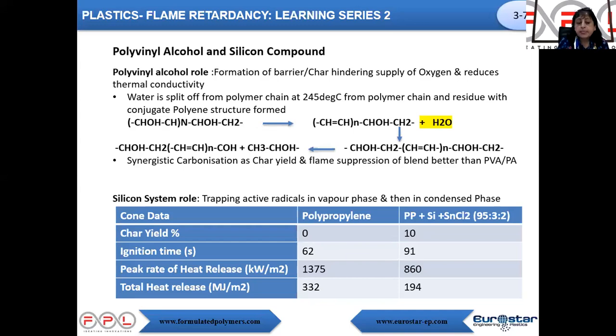But when you use them in combination, it gives synergistic carbonization, and char yield and flame suppression are much better. As an example of a silicon system, let's consider polypropylene. We took polypropylene with silicon and SnCl2, in the ratio 95:3:2. When you consider pure polypropylene, the char yield is negligible. But when we add our silicon and tin chloride systems, the char yield increases up to 10%.